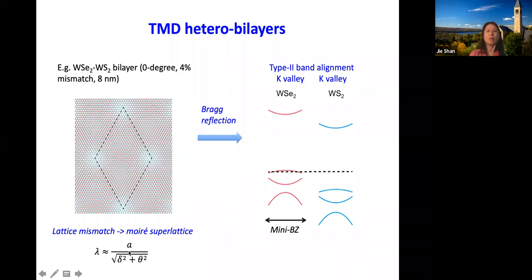If you look at the Moire period, which is given by this simple relationship, where a is the lattice constant, on the order of half a nanometer, it is large. When the twist angle theta is small, it is mainly determined by the lattice mismatch. So for 4%, we get a Moire period on the order of 8 nanometers. When the twist angle is relatively small, you can see that the Moire period doesn't change much. And that gives you this wide tuning range, okay?